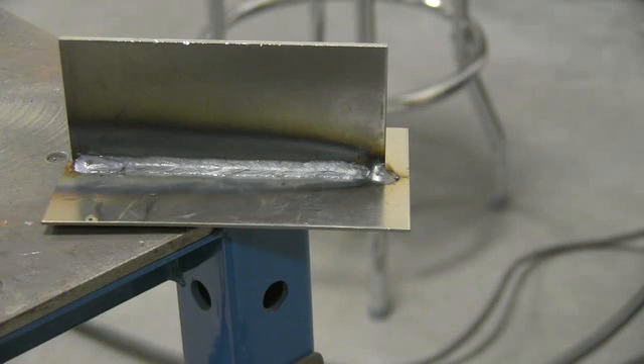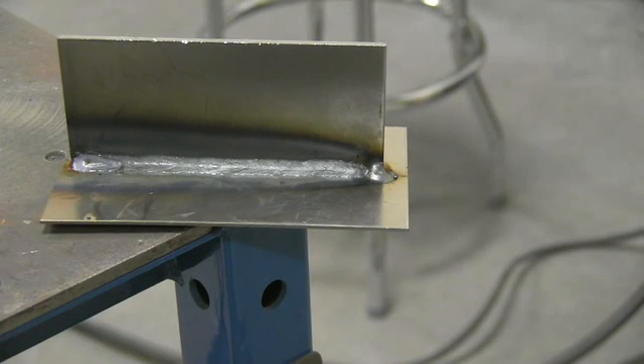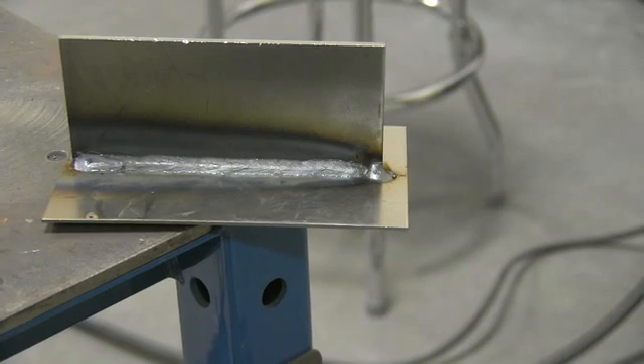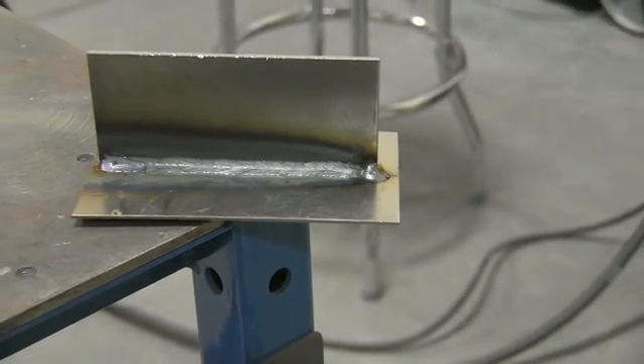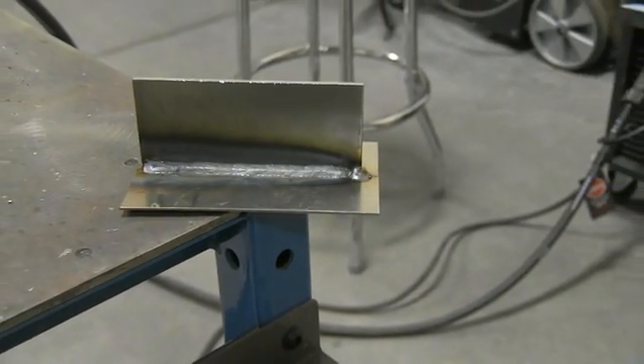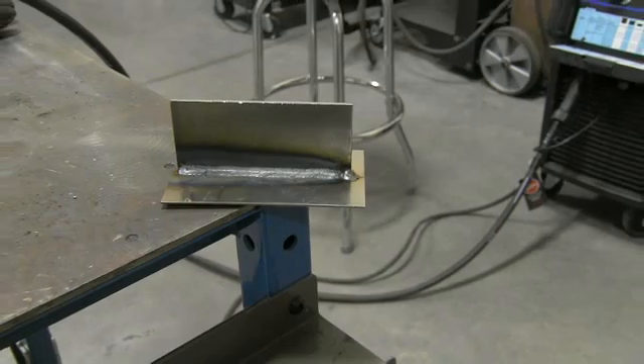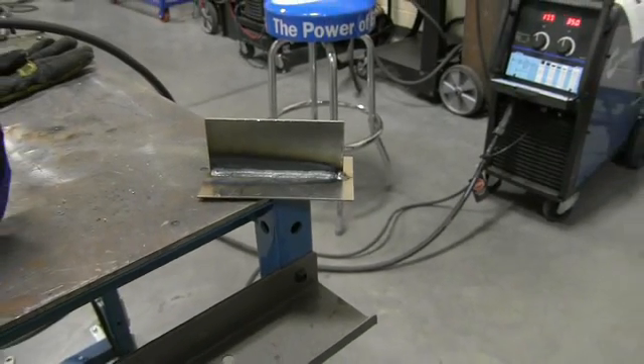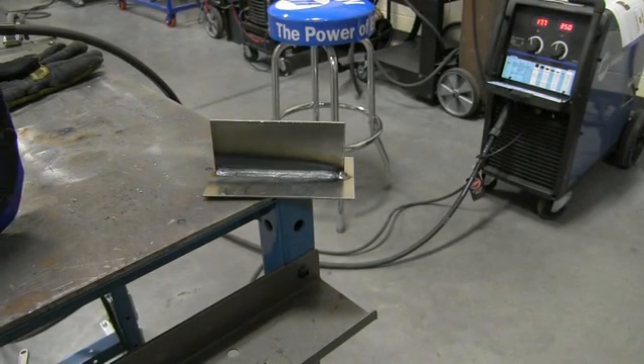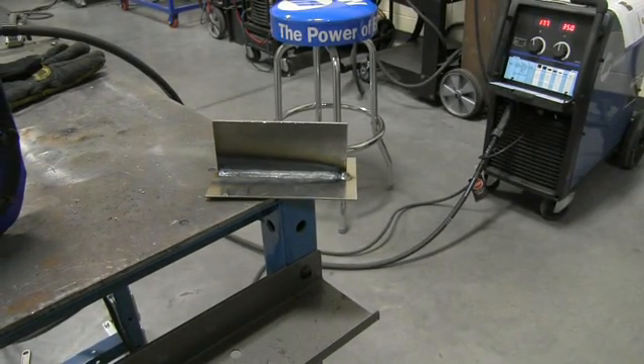So the 17.7 volts and 350 inches per minute produced a nice stable short circuit transfer, and we could tell by the sound of the arc that it was stable and producing very little spatter, as you can see from the weld bead profile. So that is how we set up the short circuit mode of metal transfer for the gas metal arc welding process.